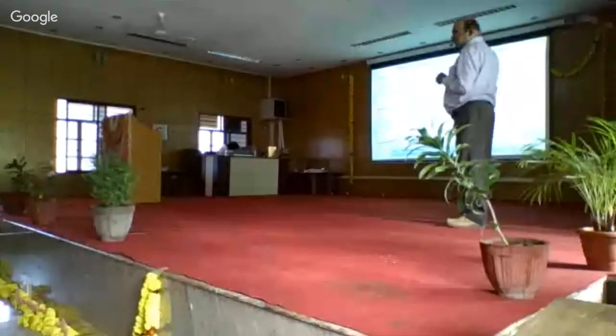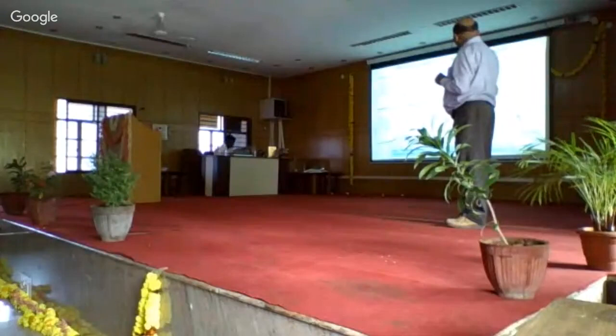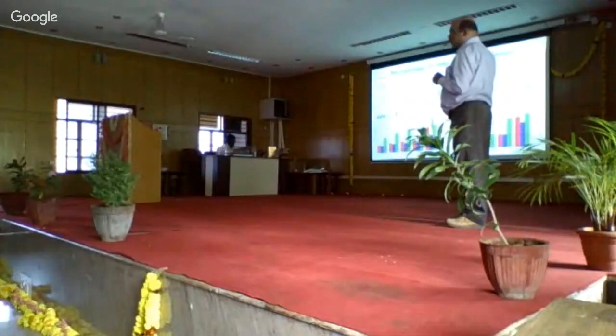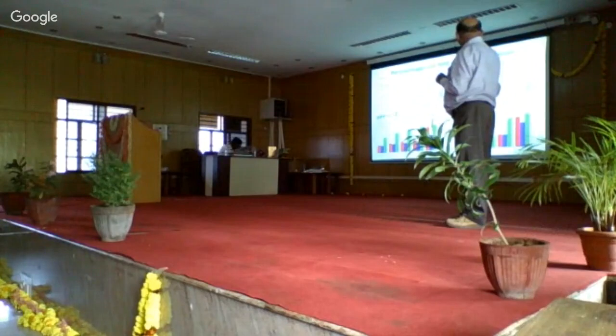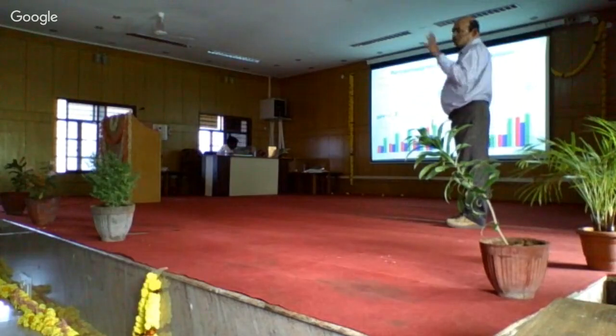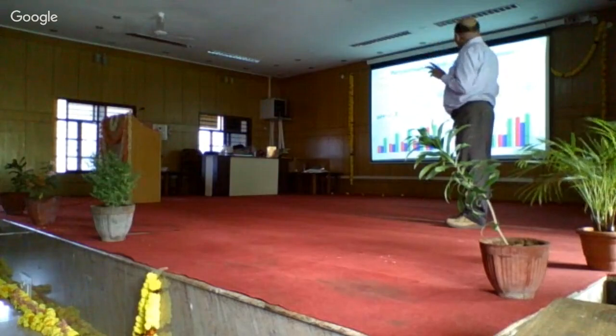We did the reaction. Here, how much percentage conversion is going? At pH 7, only 88% goes. At pH 3, you achieve 100% in 1 hour. 100% is achieved in BaWO4. CaWO4, SrWO4, all have the same structure but different band gaps. Band gap plays an important role rather than structure here. So we achieved 100% at pH 3.